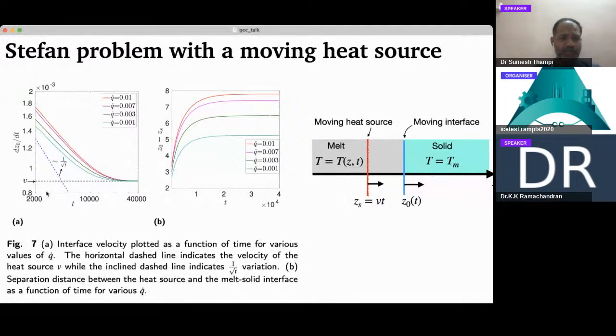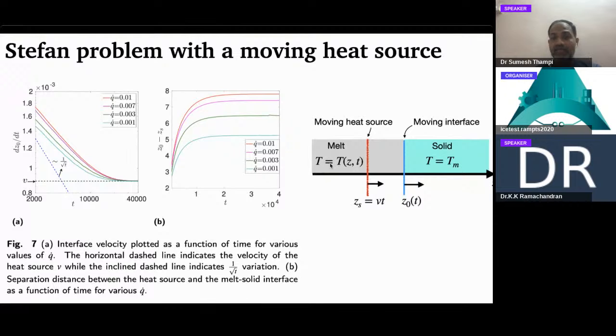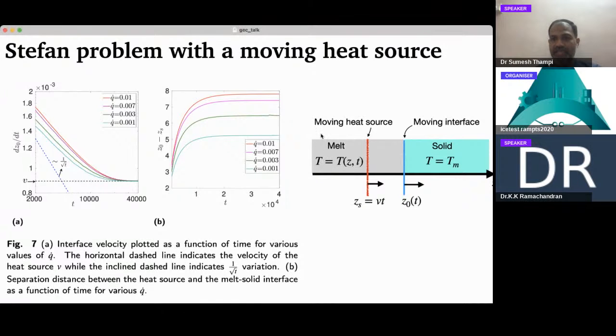Here what is plotted is the time on the x-axis and the velocity of the interface on the y-axis. So we can follow one of the curves, let's say. When you start, the heat source will be on the left hand side, and everywhere it will be solid. So that means that the solid is going to immediately melt. The velocity will be very large, but with time the velocity of the interface will become smaller and smaller. So we saw that earlier. Just as we saw earlier, the velocity of the interface continuously comes down.